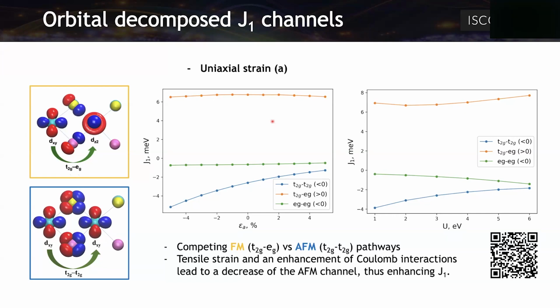Then one advantage of working with these Wannier functions and TB2J is that it allows us to have an orbital decomposition of the magnetic interaction channels. So we can observe which are the mechanisms that are competing to give these values of the magnetic interaction. And in this case, we have a competition between this mechanism that goes from orbitals that are dxy in one chromium to the dz squared in the other one. And this is a ferromagnetic interaction because it goes from one t2g orbital to an eg. The spin is ferromagnetic because it's keeping the same orientation. It can go there, it's empty.